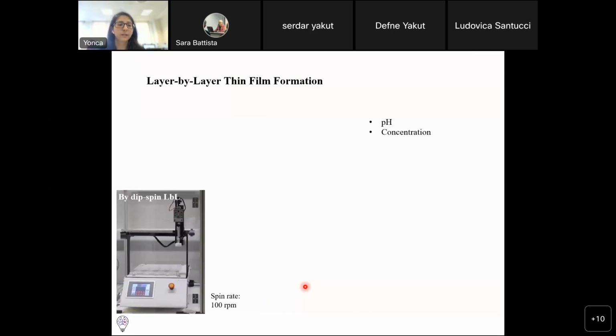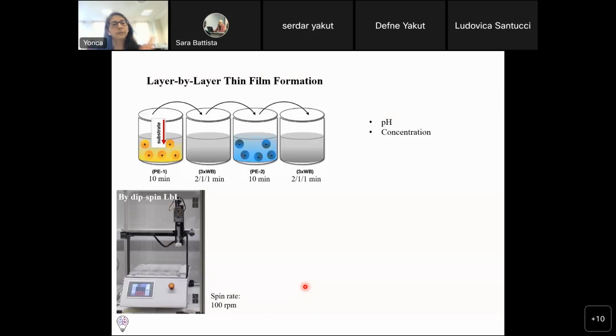In order to prepare the films, I was using a customized layer by layer device, which is dipping and spinning simultaneously. I have my substrate, and I have the solution I need to deposit. I'm dipping and spinning my substrate at 100 RPM for 10 minutes. Then I take out the substrate and put it into 3 different water baths so that I can rinse the surface and get rid of the excess material. Then I'm dipping and spinning my substrate again to deposit the oppositely charged material on the surface. I do it for 10 more minutes and then rinse it again.